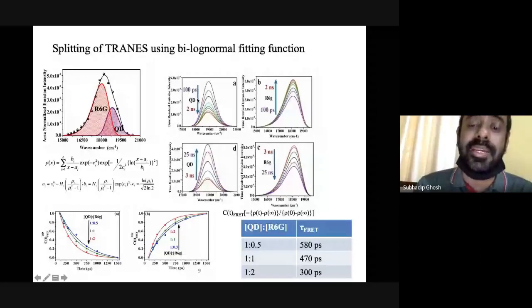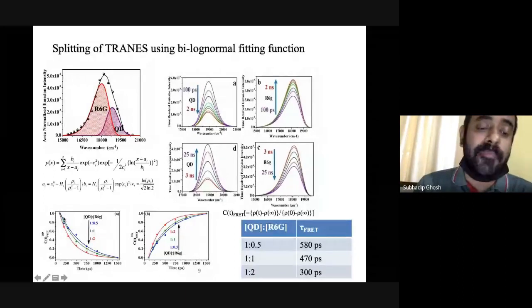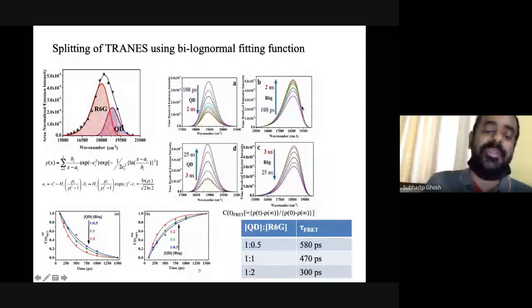Here it is increasing. Now, if I plot the area under the curve as a function of time, we get this kind of decay curve for the quantum dot and a rise curve for rhodamine 6G. Why a rise? Because the intensity of rhodamine 6G increases.